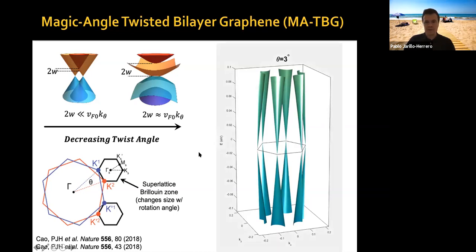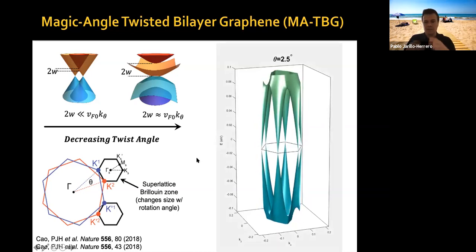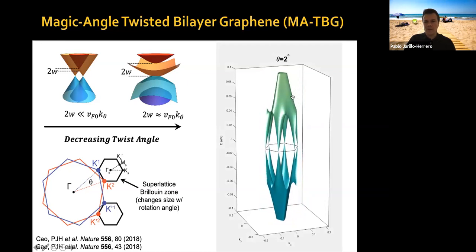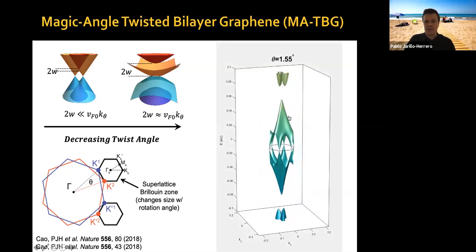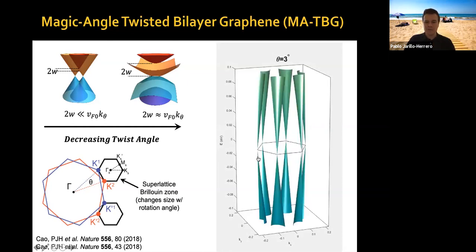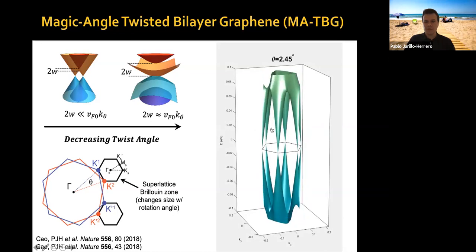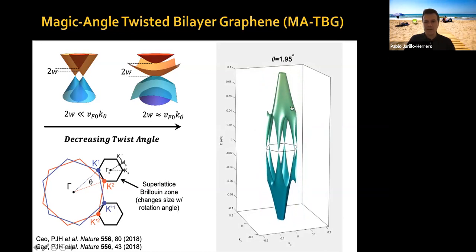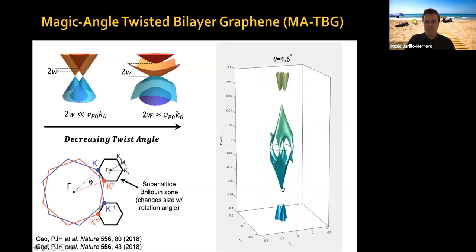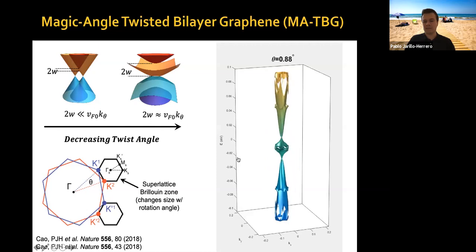So if I run this video, you can see that the Brillouin zone is becoming smaller. Now you see within this energy window, a set of bands begins to flatten. They're separated by band gaps. Now there's a flat band condition there. And then the system continues to evolve in a complicated manner. Let me just run it again, okay? You see two important things happen. One is these gaps, and the other one is these bands, which become flatter and flatter, and at about 1.1 degrees, they become very flat, okay?